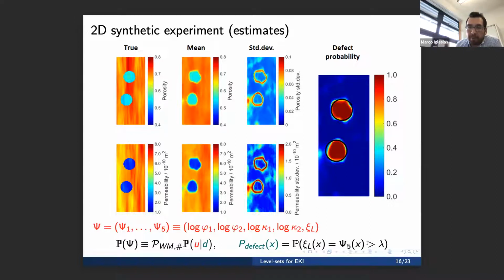So I can compute a probability map that tells me how likely it is that at a given point I have a defect. That's what we've done here, to show that indeed the almost 100% probability is inside the region where the defects were in the synthetic case. So that was very good, very accurate, very promising that we can actually do that in synthetic experiments.